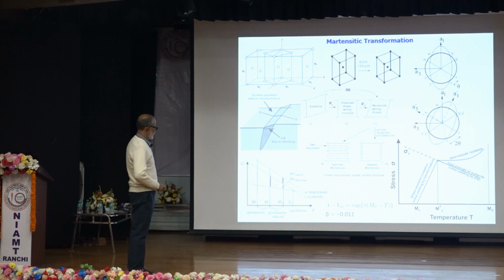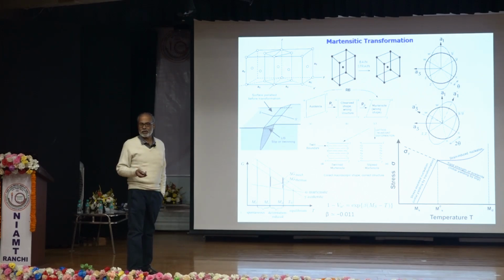And that can be stress or strain. How does stress and strain induce the transformation? If you follow the yield stress of a material, it reduces with temperature, right? So if you apply certain stress, that may bring in certain transformation elastically. That is elastic transformation. It will be reverted. Even if there is a transformation, that will be reverted. So it is basically elastic transformation up to yield strength. But above yield strength, there will be permanent deformation and the transformation will be permanent, right? So we call it Ms sigma up to yield stress, and the permanent deformation which induces martensitic transformation, we call it Md. So it occurs between Ms and Md temperature.